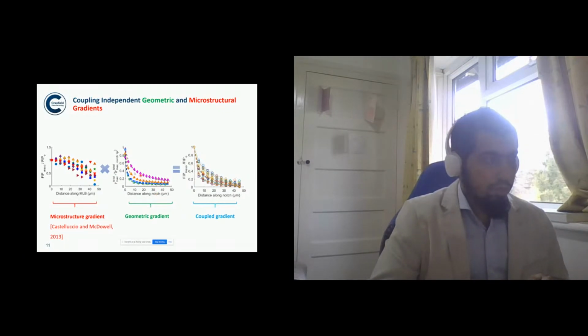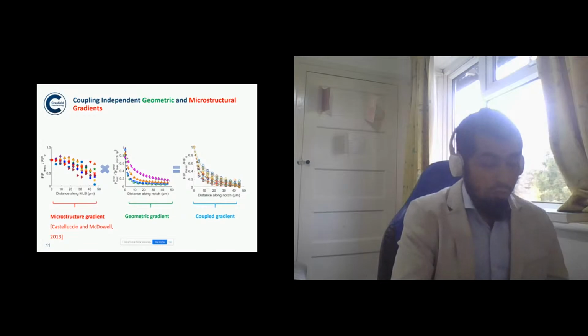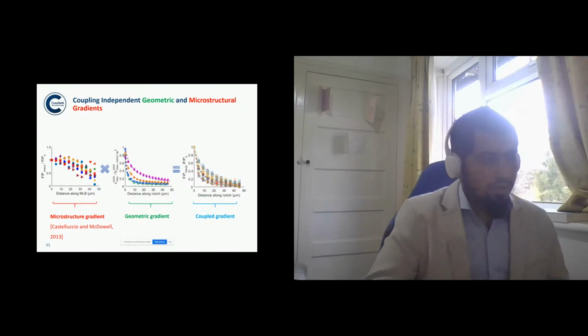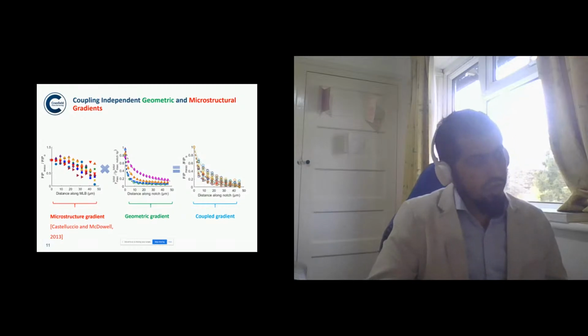So we independently couple it with the explicit microstructure gradient to reconstruct the independent coupled effect of both gradients. And this is done by the economical model that is less computationally intensive. Now we compare this result with the expensive crystal plasticity simulation, and we found that this is roughly the same with some level of uncertainty. So thereby this is in good agreement.